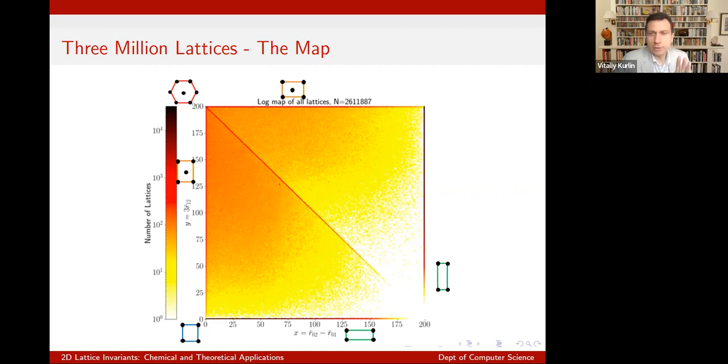So to summarize this plot, let me only add that it was a bit surprising that despite this preference for high symmetry, say 3 rectangular lattices for each primitive orthorhombic crystal, in the yellow triangle in the generic case you have 45% of oblique lattices.